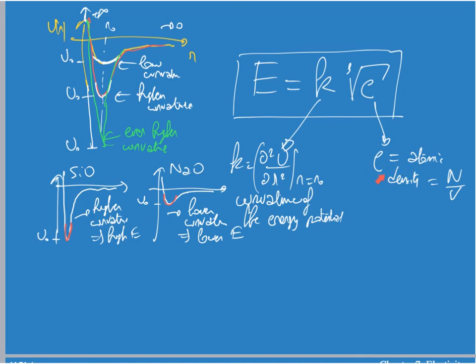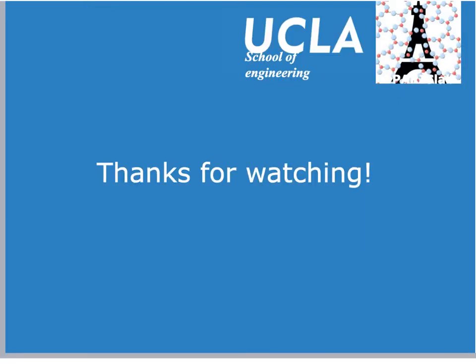And then you have this second effect, which is the effect of how many atoms you have per unit of volume. And here you can see that the more atoms you have per unit of volume, the more little springs you will have within the atomic network, so the higher will be the Young's modulus. Okay, so that's all you need to know for the stiffness of glasses. Again, the main conclusion is that the stiffness depends at the same time on the connectivity of the atoms and the packing of the atoms. How many atoms do you have per unit of volume? How much internal porosity do you have in between the atoms? Those are the two main ingredients that will control the stiffness of glasses.